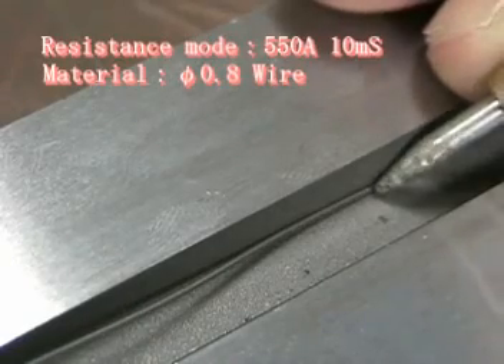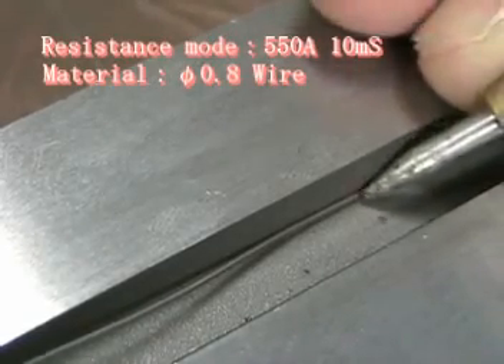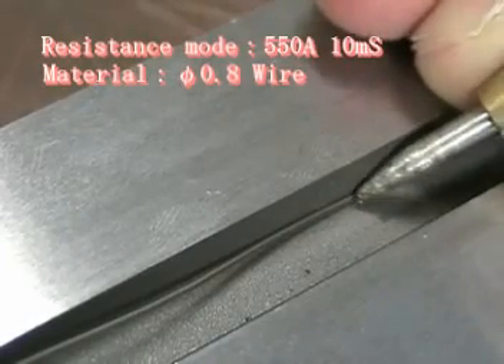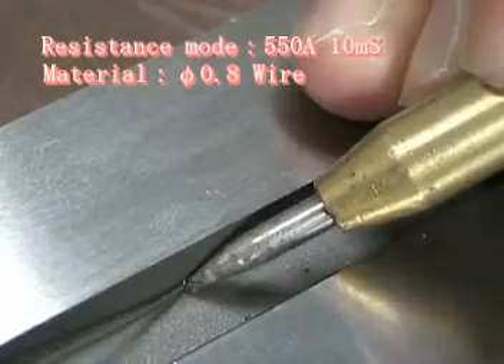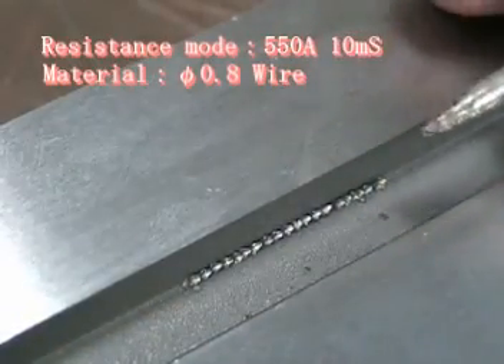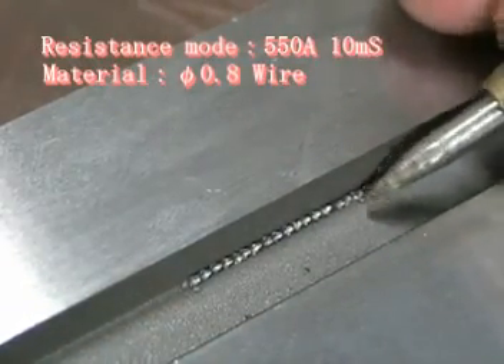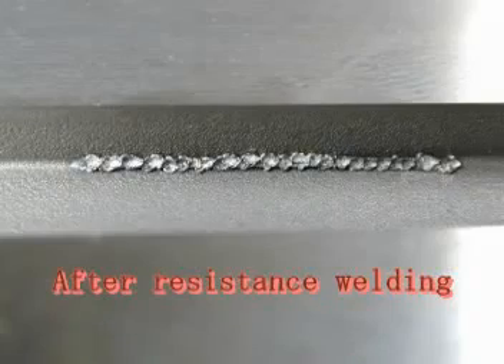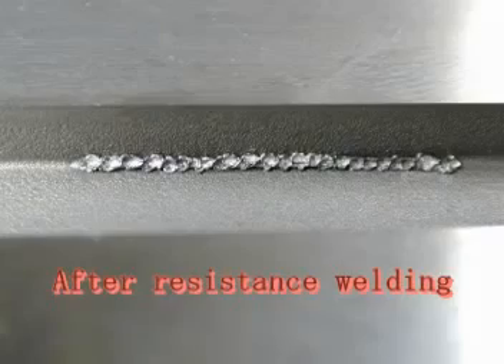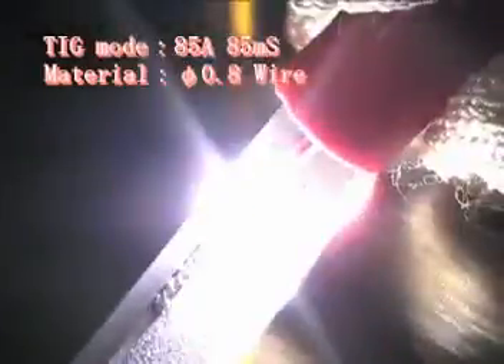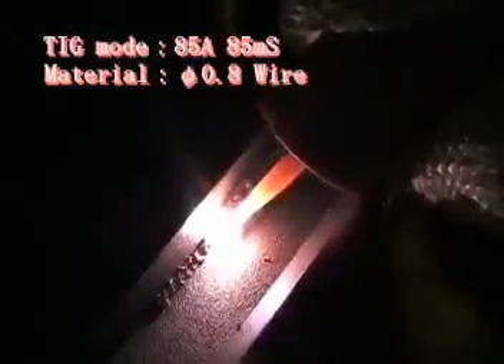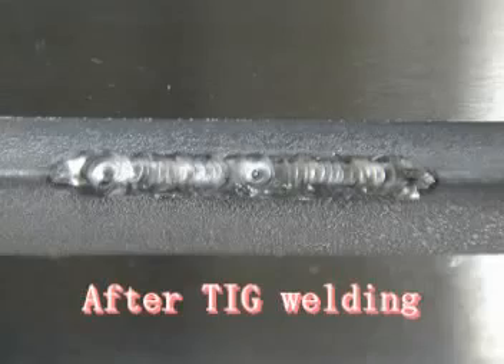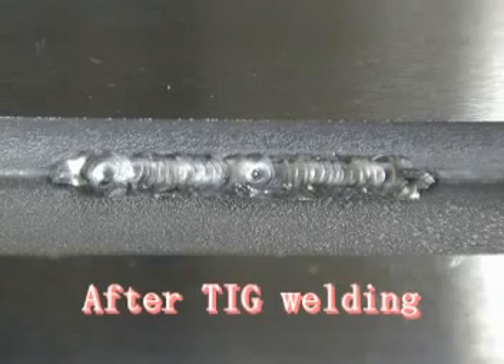First, join the welding materials temporarily by using the resistance welding mode. Avoid any clearance between the base materials. Fix welding materials temporarily in this way. In the TIG mode, move the electrode slowly to overlap the weld bead slightly at a 45-degree angle with a clearance around 1.0 mm from the welding material using the continuous mode. Then it is completely welded in this way.